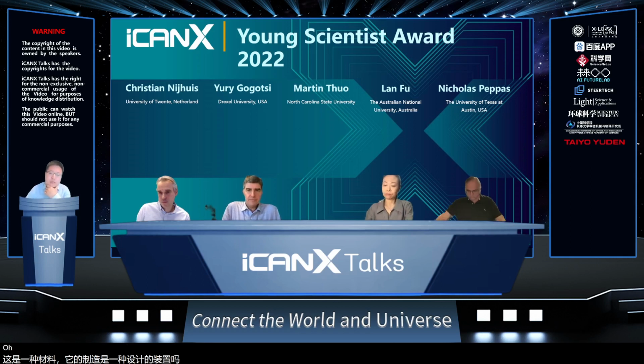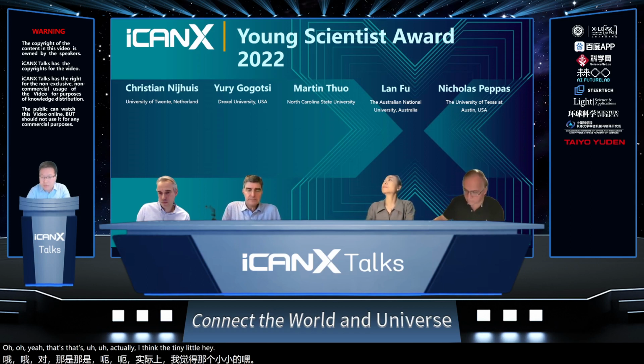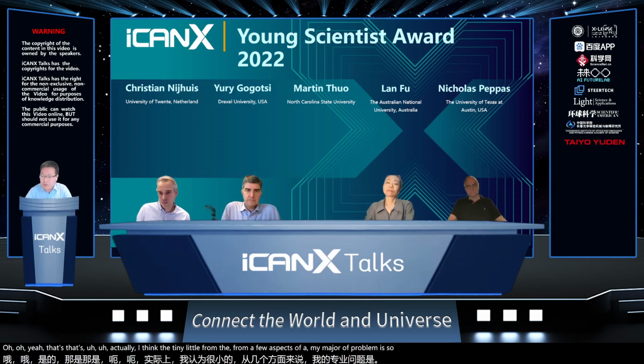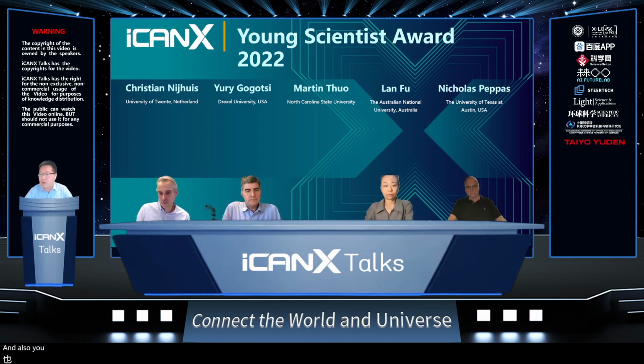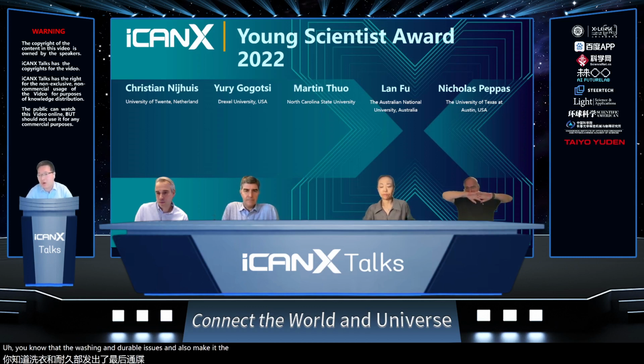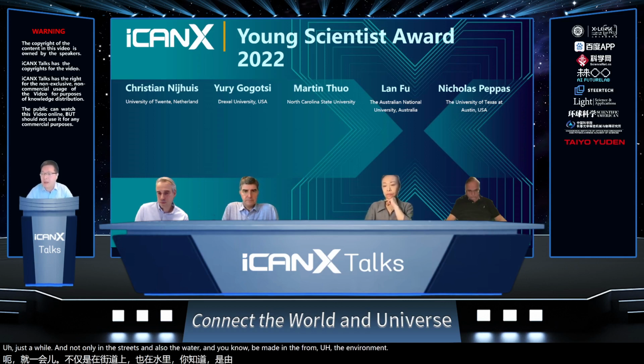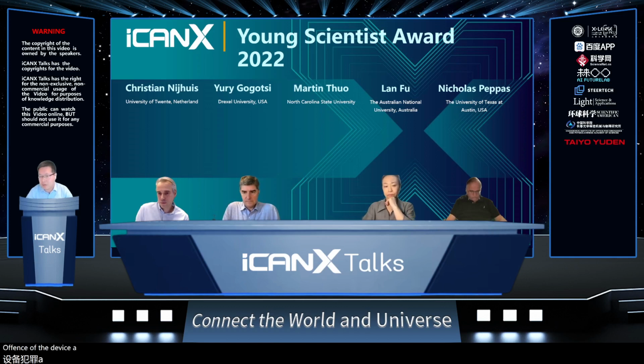Thanks for that question. I think the challenge comes from a few aspects. One major problem is the interface issues, the interface bonding strength, and also these are porous structures. When you print, you also need to do some specific treatment to maintain a stable, reliable interface. Another issue is that for textile-based devices, we need to accommodate washing and durability issues, and make them more robust to survive not only strains but also water, humidity, and the environment. Water and temperature changes can affect the device performance.